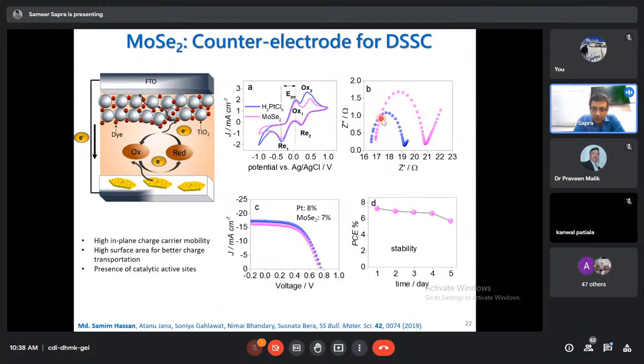Of course, molybdenum selenide has a slightly higher resistance, but we replace this platinum with molybdenum selenide, and with platinum you're getting typically 8% efficiencies in these N719 dyes. These are, I would say, the best reported efficiencies, between 8 to 9%. With molybdenum selenide you're getting about 7%. You lose 1% over here, but then you're making much cheaper devices.